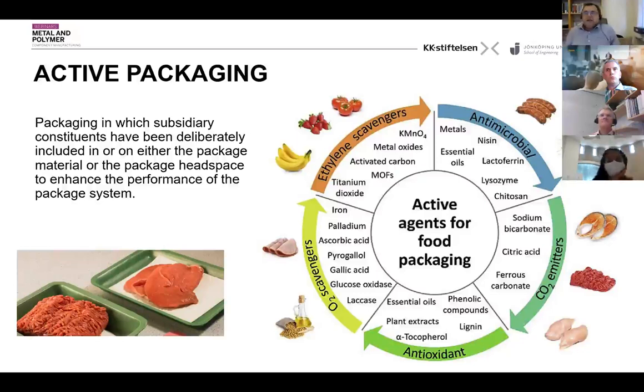Similarly, antimicrobial elements could be incorporated in the sachets. Say, for example, we discussed the role of carbon dioxide in coffee. Freshly ground coffee produces a lot of carbon dioxide gas. So this gas could be eliminated from the packaging by using, for instance, calcium hydroxide, which catches the carbon dioxide and therefore eliminates it from the atmosphere of the packaging. And so on, we can give different kinds of examples, like oxygen scavengers. For example, iron powder or ascorbic acid could be used as the oxygen scavenger. So there are a number of ways of enhancing the barrier properties of the polymer. Next slide.